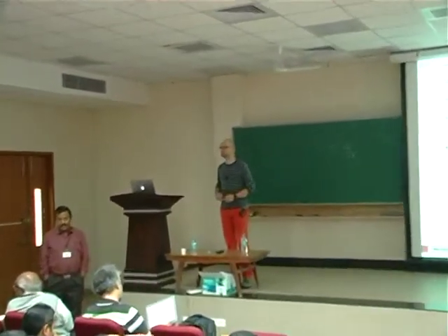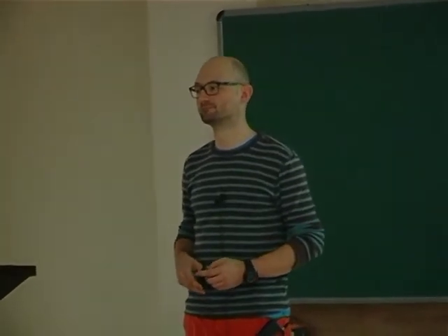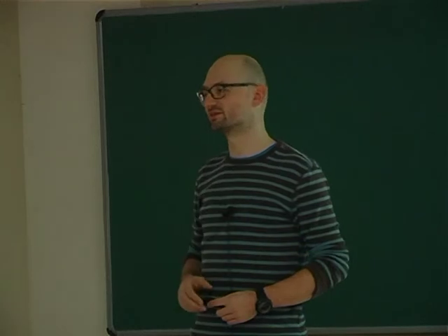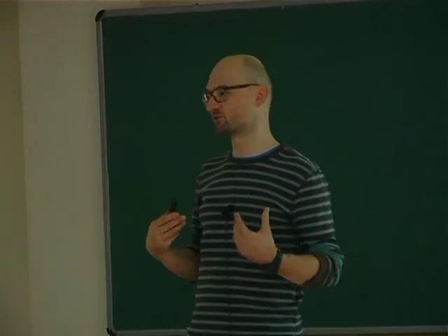And the other thing is, I'm surprised that you say a localized spin model description is not good for strontium ruthenate, because what we did was we took LDA calculations, extracted J1, J2 in an extended Heisenberg model, and explained experimental data of the variation of the effective moment per site. If we treat it as an effective moment, we could get a very good description of all the experimental data. That's still one of these puzzles that's not well resolved for me, actually.